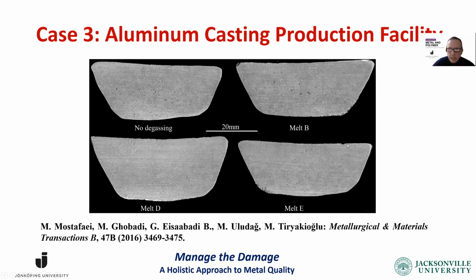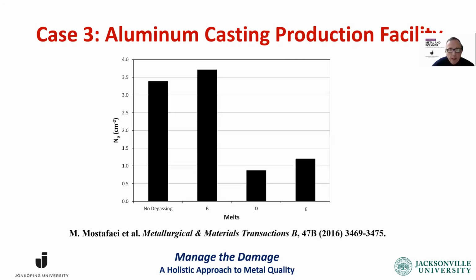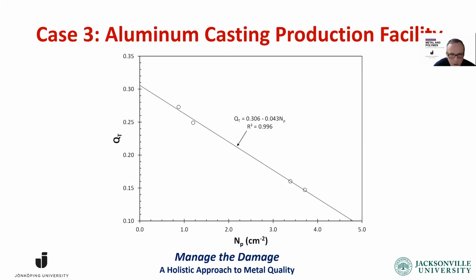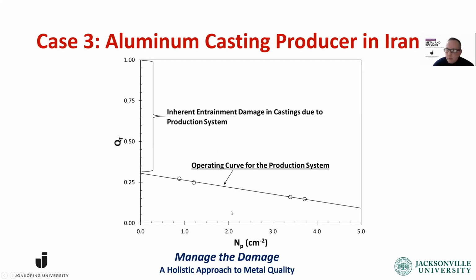We published this several years ago. I think my co-worker Gassem is also in the audience. And we reported, okay, how can we optimize the degassing procedure? Sometimes degassing can damage, and we can actually see it. Some of the times we can't because hydrogen is gone. But when we plot the data along with tensile tests, this is what we saw. The number of pores on these RPT specimens versus the tensile tests. When we zoom out, this is the operating curve of the system. And again, it's the same story. We lose about 70% due to the inherent damage in the production system.